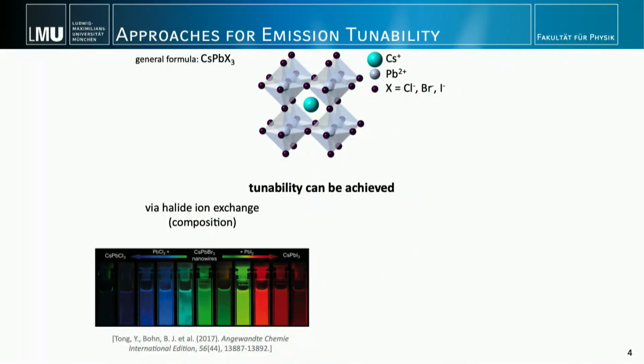Based on the band gap, so the energy difference, this light can have different colors. So in the end, this will decide if we have red, green, blue emission, or even colors which we cannot see. So generally, the emission can be tuned in two ways. First, via the material composition. This is shown here. Using iodide, we get red emission. Using bromide, we get green emission. And using chloride, we can achieve blue emission. But as you already see in this picture, the blue efficiency is very low, and also these nanocrystals are not stable. So this does not work proper enough.